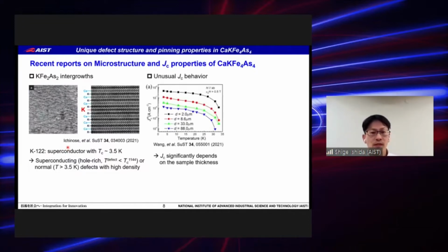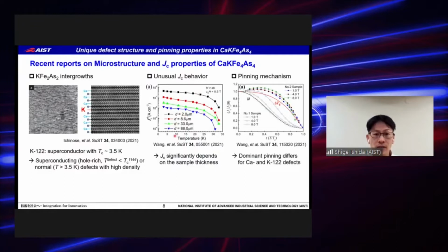Regarding the JC properties, it will be demonstrated that JC significantly depends on the sample thickness. By making the sample thinner and thinner, JC goes up by a factor of 10 or more. Additionally, a comparison between single crystals with different defect structures showed that the dominant pinning mechanism is different for crystals with calcium 122 and potassium 122 intergrowths.